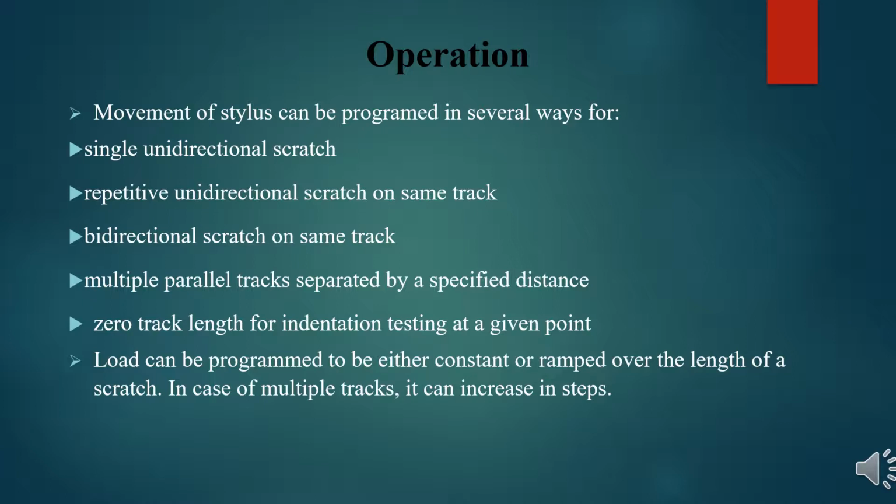During operation, the movement of the stylus can be programmed in several ways using the machine controller unit. The scratch may be single unidirectional, repetitive unidirectional on the same track, or bidirectional on the same track. It can also be multiple parallel tracks separated by a specified distance, or zero track length for indentation testing at a given point. The load applied during the testing can be programmed as constant or ramped over the length of the scratch. In the case of multiple tracks, it can increase in steps.